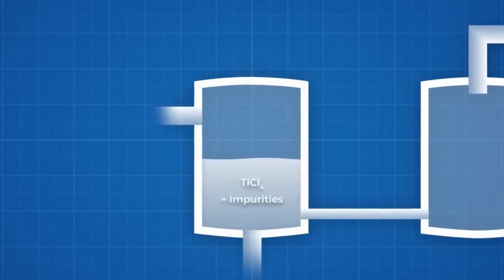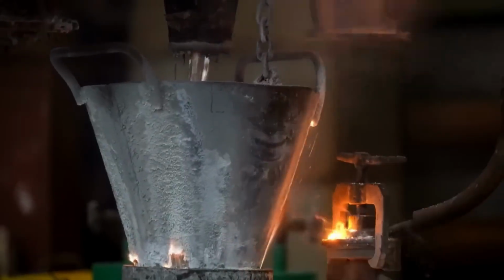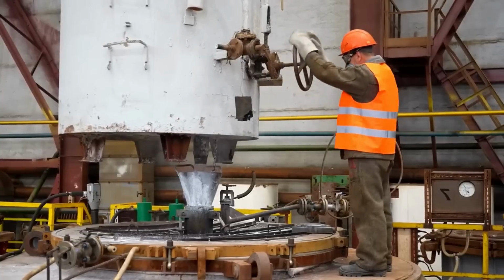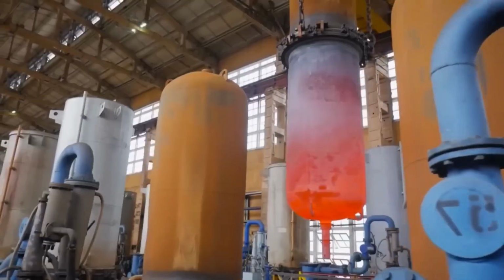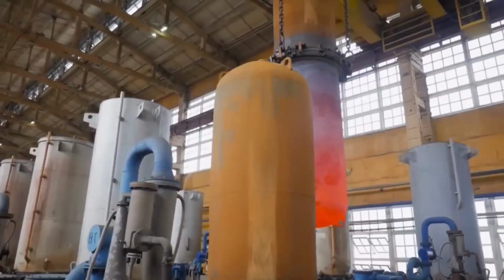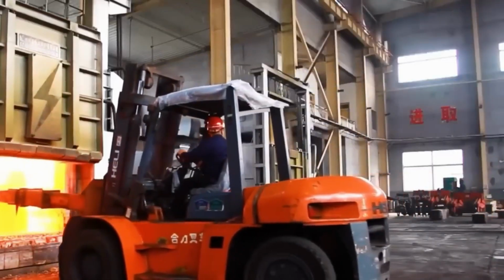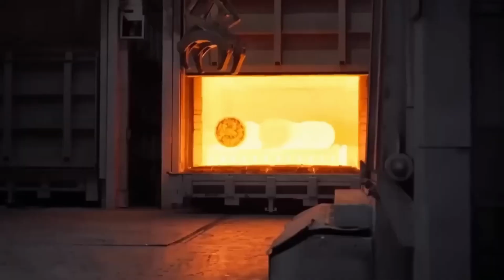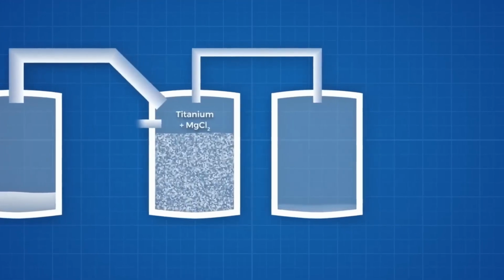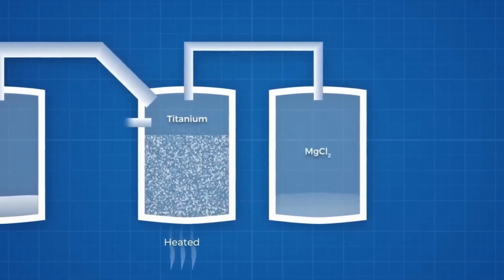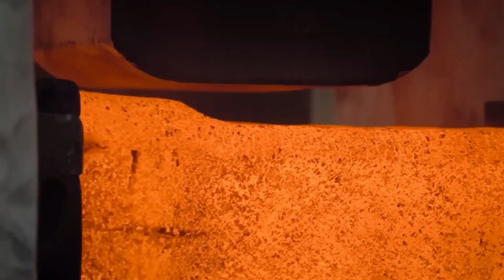Unlike continuous steel production, the Kroll process operates in batches. The reactor is loaded, the reaction takes place, it is cooled, opened, the sponge is removed, the system is cleaned, and the process begins again. This batch nature explains some of titanium's high cost. It is not produced in huge liquid streams like iron or aluminum, but in controlled cycles where each batch must be verified. The purified sponge is crushed, sorted, and analyzed.